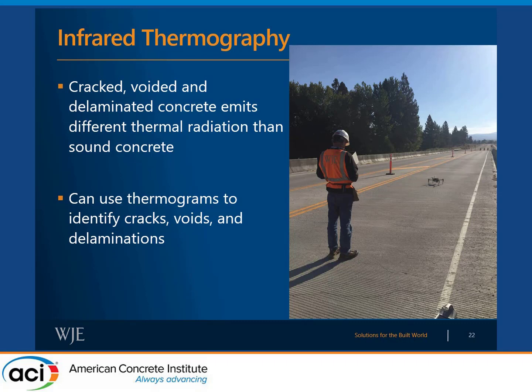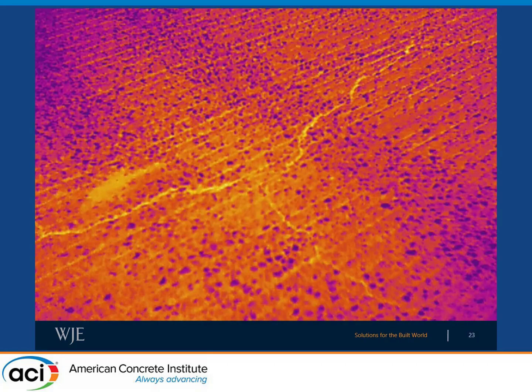So this is one of the bridge decks I had shown previously. We've got our UAV and it's got an infrared camera on it. And so I showed this picture previously where we could see the crack. The reason why the crack is visible is because we actually took this as the sun was starting to set that particular day. So the concrete internally was very warm and the surface was cooling off.